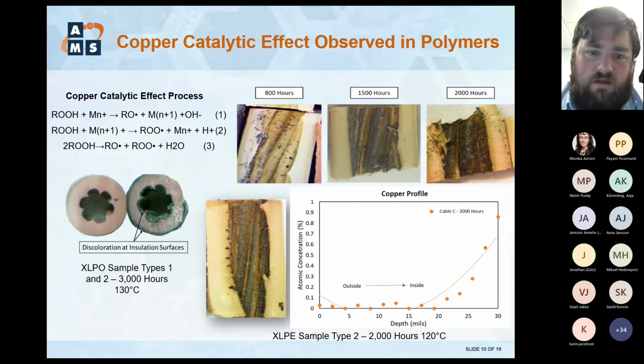And so that's what you see, the black region that develops, all this blackening. That's a direct result of the copper catalytic reactions going on at the interior surface of the insulation. And you can see how it progressively worsens with increasing aging time. This data is taken at 120 degrees Celsius.